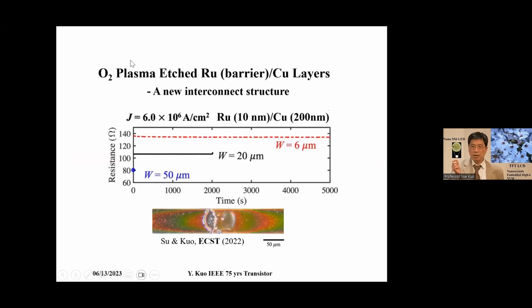And for copper interconnection, as we all know, a recent study shows that when copper is made into fine lines, an issue comes out. Resistance becomes very high, and the electromigration life has a problem. So we further introduced ruthenium as a barrier layer for copper. The advantage of this is that copper can't be etched by oxygen, but ruthenium can be etched by oxygen plasma. So the whole new ruthenium-copper stack for interconnect lines, we use oxygen to etch, and electromigration shows high reliability because ruthenium electromigration life is longer than copper. So this kind of structure has long lifetime.